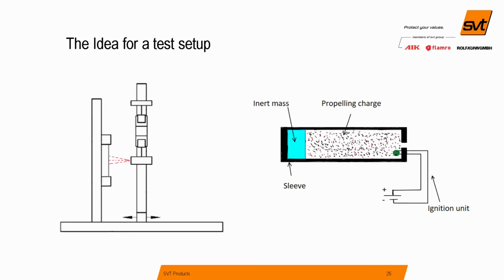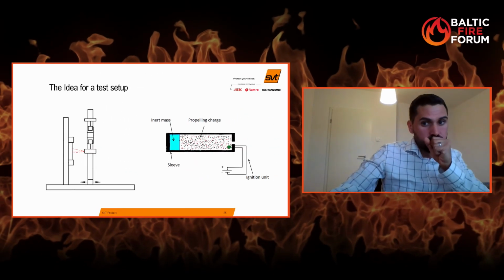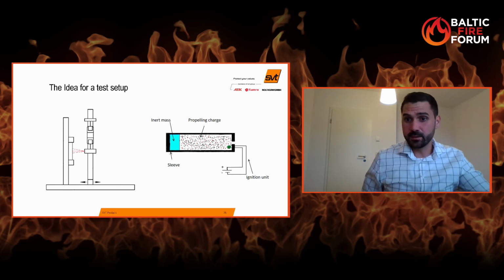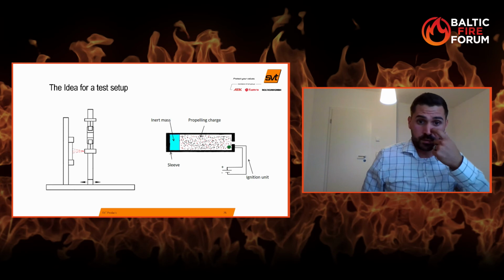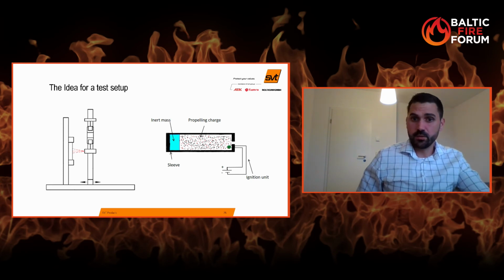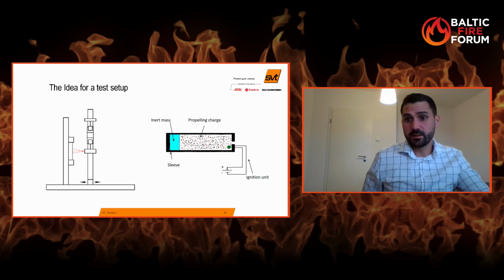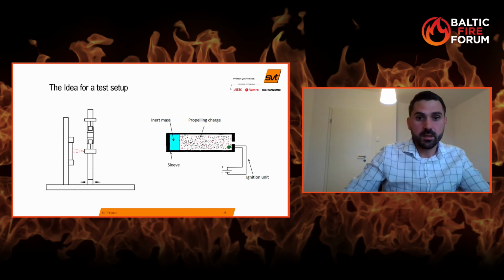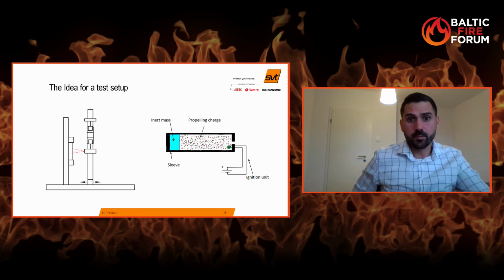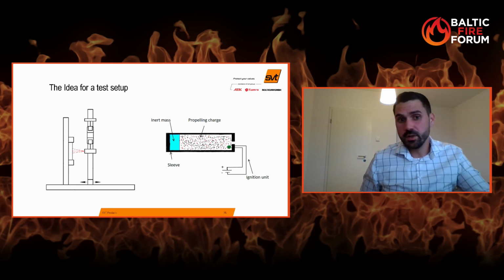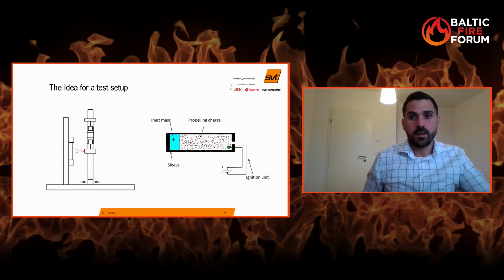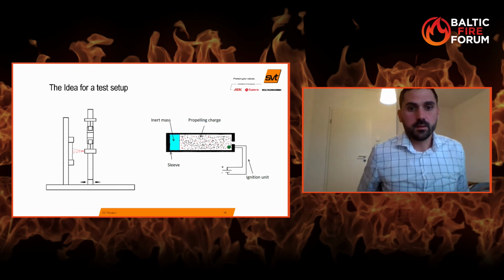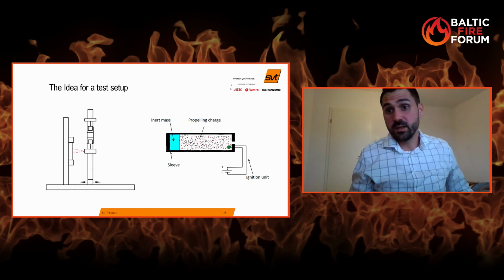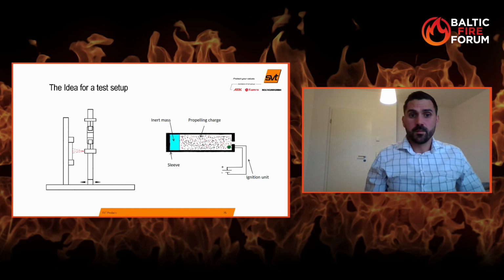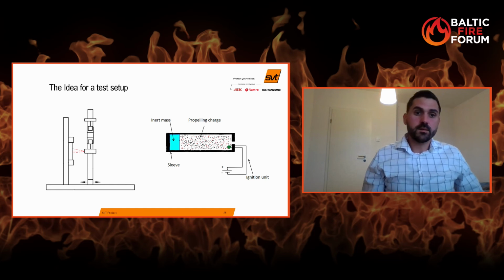So we got in contact with some partners and built a really small but really effective test setup to check our materials, to check if they can withstand these high requirements in the case of a battery fire. As you can see here, it's a test setup. You have your inert mass, your propelling charge, all in the sleeve in the ignition unit. Then you have your substrate, and 2 centimeters, 20 millimeters, is the distance from the end of the inert mass to the substrate.